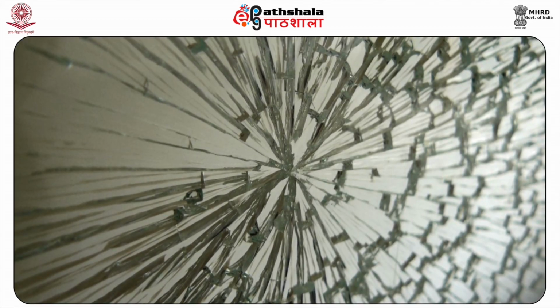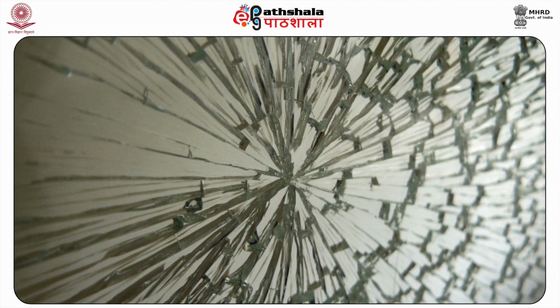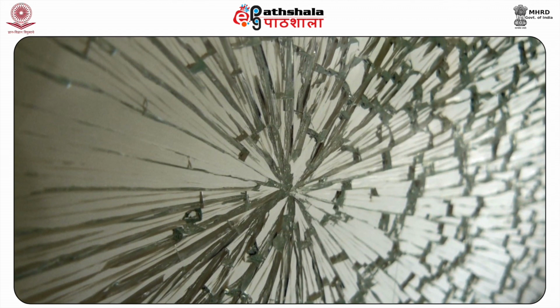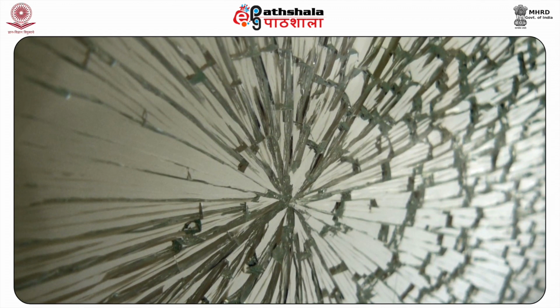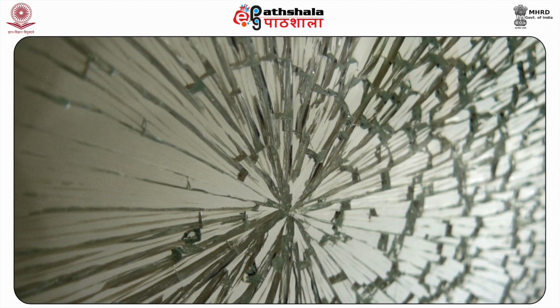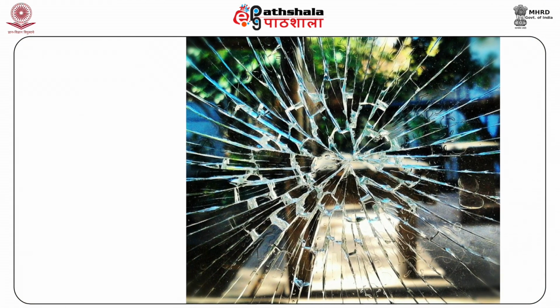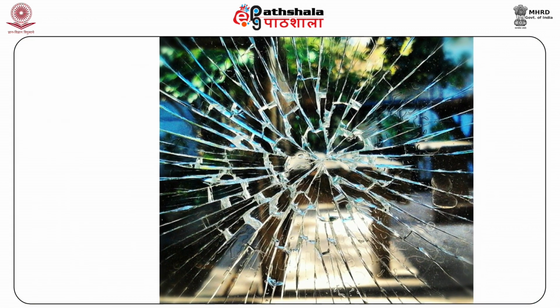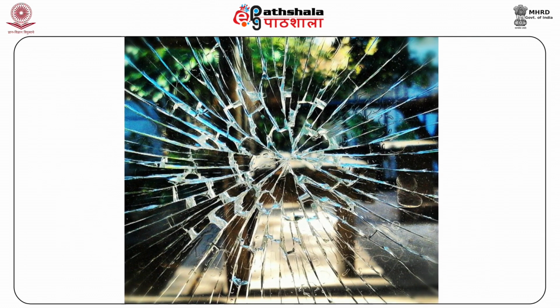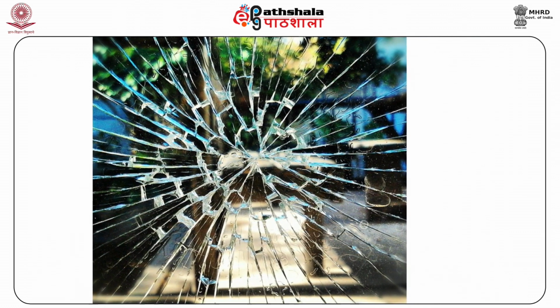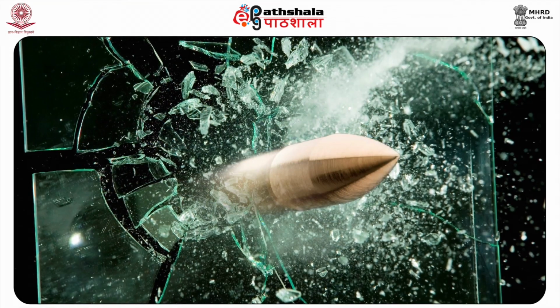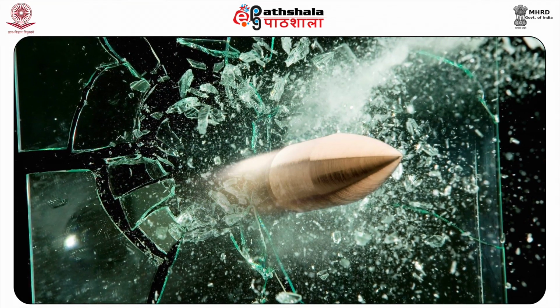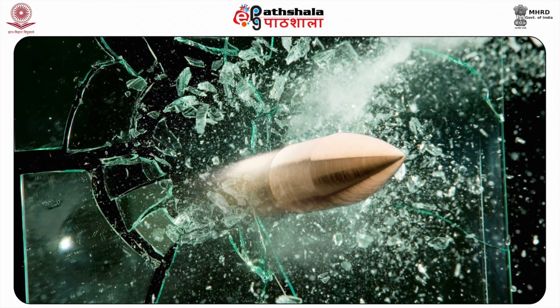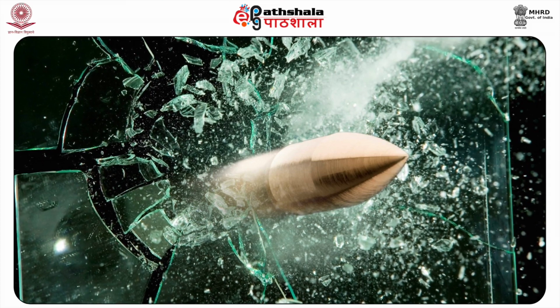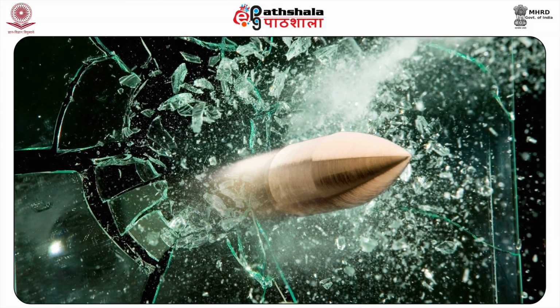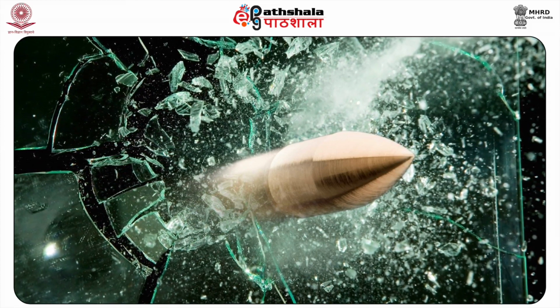In a glass sheet, the primary or initial rupture, which we call radial fracture, tends to be star shaped or appears like spokes of a wheel. In other words, it spreads from the point of contact as a series of cracks in a number of random directions, as shown in the figure. For example, penetration caused in a window by a projectile or a bullet produces a pattern in which cracks radiate outwards and encircle the hole.